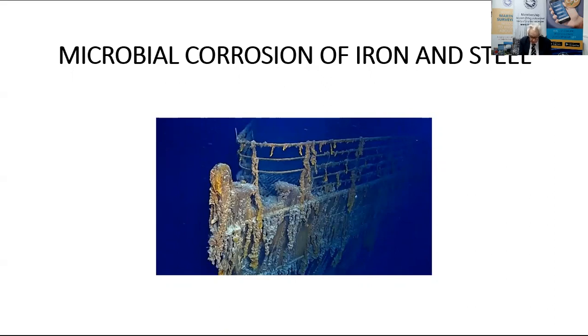The author realised the severity of the problem some 40-odd years ago when employed as a superintendent engineer for a company running a number of general cargo Liberty ships, which often loaded ballast water for return trips from the West African coast. The ballast water was, from the nature of its loading from the rivers, often heavily polluted with vegetable matter and very muddy. On inspection of the ballast tanks at one of the classification surveys, very severe pitting of a clearly defined and characteristic type was frequently found under the mud deposits in the tanks, and a great deal of time and money was spent trying to find the cause of the problem. It was eventually identified as microbiological in origin when specimens of the corroded steel were sent for laboratory analysis.